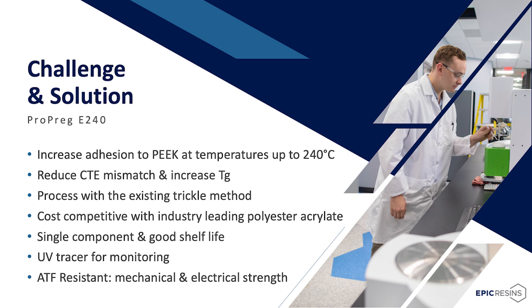It is vital that the material must drop in with the existing trickle equipment without a loss of process throughput. It must also be able to maintain, or better yet, reduce cure cycle time and lower the oven temperature in the bake zone. It is important that the material be cost competitive with leading industry polyester acrylate and be a single component with good shelf life at 25C. Having a UV tracer for visual and video monitoring is vital in processing.